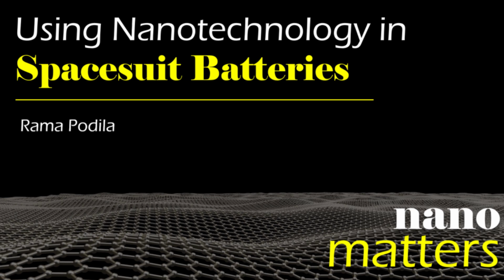So what we did was we used a combination of carbon nanotubes and silicon nanoparticles to come up with an anode architecture in such a way that this pulverization of silicon is no more a problem, and that we can have long life cycles up to 1,000, 2,000 cycles.